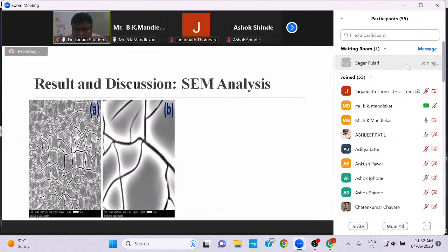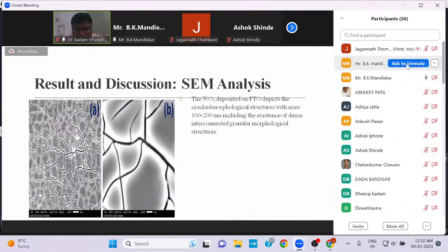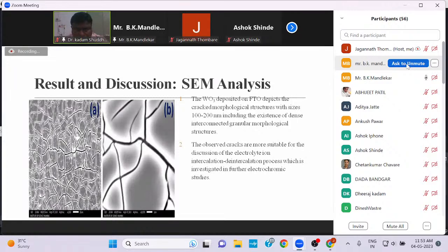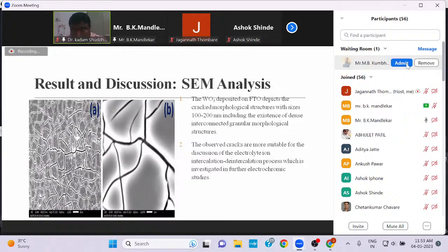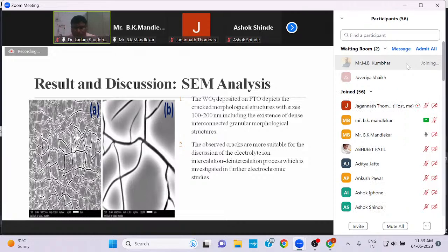Then we have done the SEM analysis. In SEM analysis, we found this crack morphology. The WO3 deposited on FTO depicts a crack morphology with structure sizes of 100 to 200 nanometer, including the existence of dense interconnected granular morphological structures. The observed cracks are more suitable for diffusion of electrolyte in the intercalation process, which is investigated in further electrochemical studies.